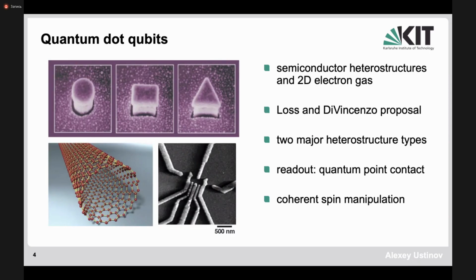Sometimes people call the quantum dot a piece of carbon nanotube, which can be controlled by gates. For example, you could localize electrons in a small fraction of the nanotube and then operate it as a quantum dot as well. But most common are quantum dots which are actually produced by electron beam lithography by lateral confinement. So you basically make a two-dimensional electron gas, and then you confine the electron gas in a particular area by using metallic electrodes on the surface.